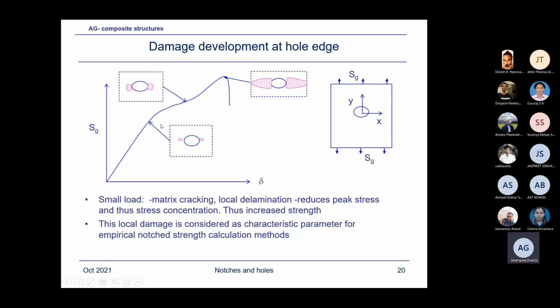So as we start loading the laminate, at smaller loads, some kind of small damage starts. Initially, what will happen is in the 90-degree fiber layers, the matrix will start cracking, transverse to the load direction. It is the 90-degree plies, right near the notch or the hole tip, because there are high stresses. So naturally, when the stresses are high, it will lead to damage initiation. So the first damage will be matrix cracking. And then the damage size will keep on increasing: matrix cracking, fiber splitting, some kind of delamination, all sorts of damages could occur depending upon the layup. And then you would find a significant amount of damage, and finally the fracture would occur.